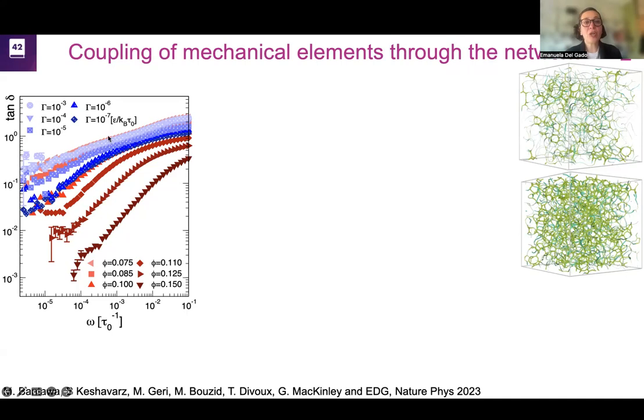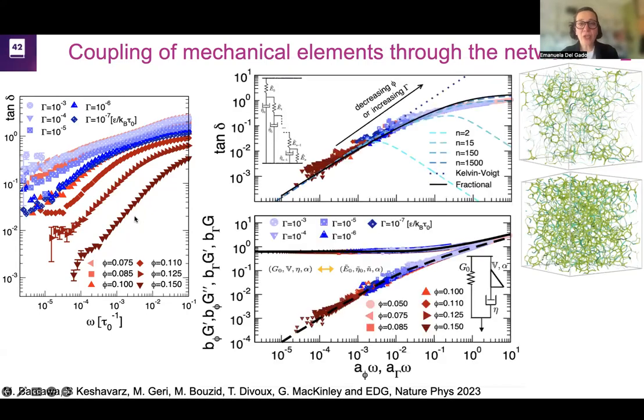This is the rheological response. We measure the tan delta here, which is the ratio between G double prime and G prime, as a function of the frequency. As we vary the volume fraction or the kinetics of the aggregation in the simulation, this tan delta goes all over the place. However, you can in fact construct a master curve of all this rheological behavior, which is very interesting. You can shift the frequency in this plot on the left to make your tan delta overlap into a unique master curve for all of these gels.